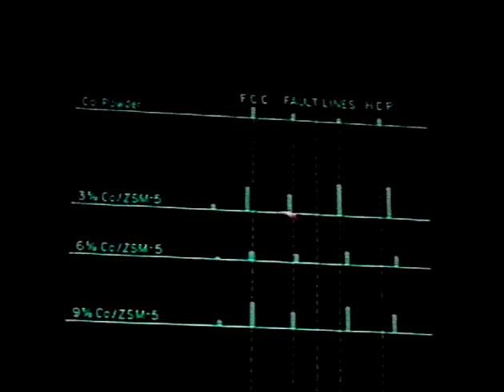Now what happens is when the particle size goes down from say 40 nanometers to 10 nanometers, you have the cobalt particles reduced to now single domain particles.